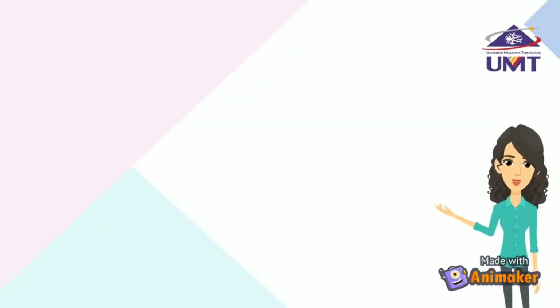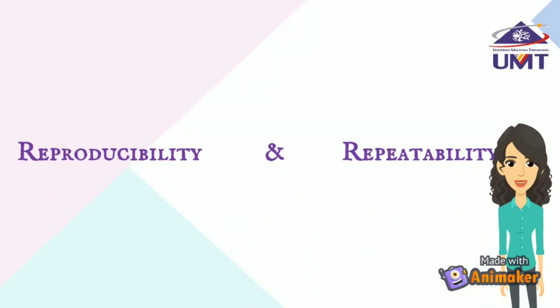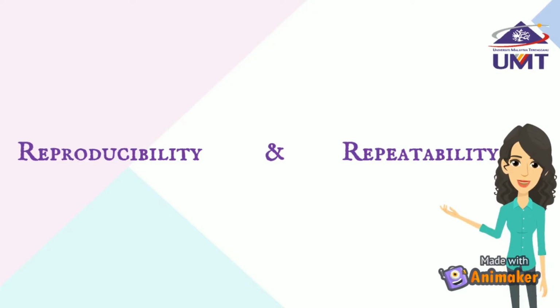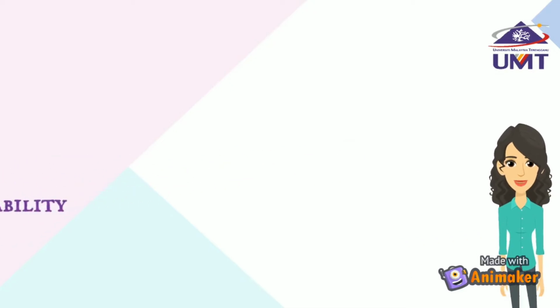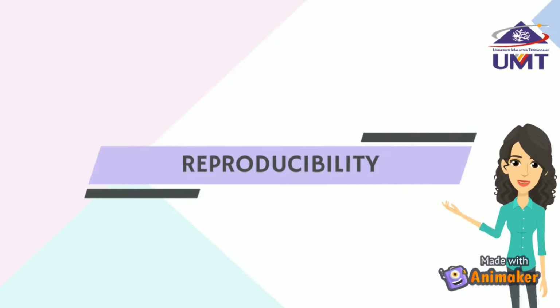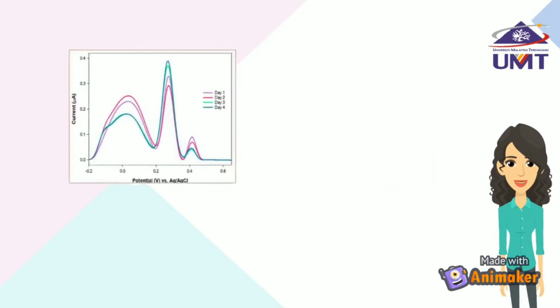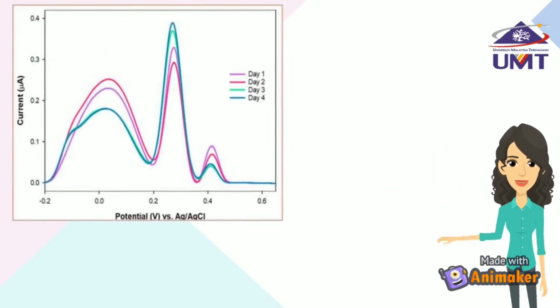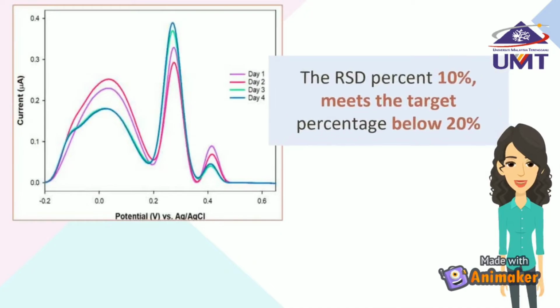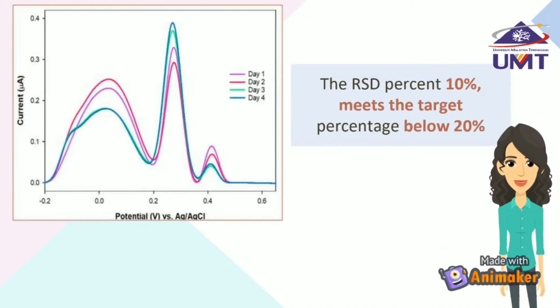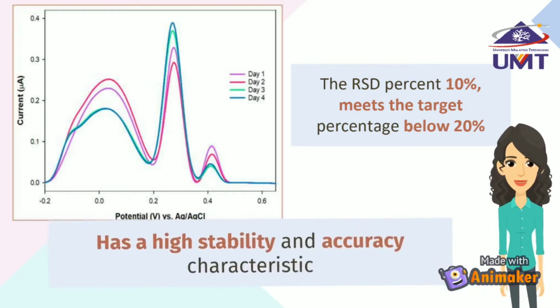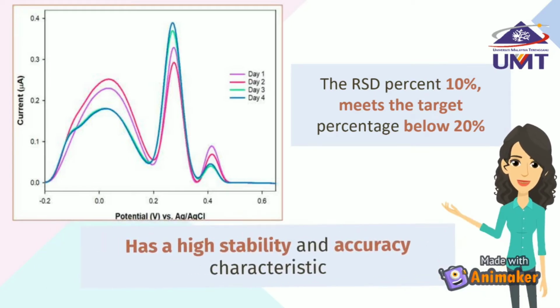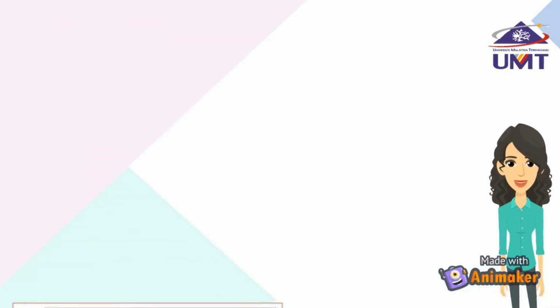Our product's effectiveness is proven based on the reproducibility and repeatability of the modified electrode, to ensure the best product is obtained. The reproducibility step was done based on the measurement of agreement on identical tests under different conditions with the same process. The results obtained a 10% RSD value which meets the target percentage. Hence, we can conclude our product, the modified electrode, has high stability and accuracy.